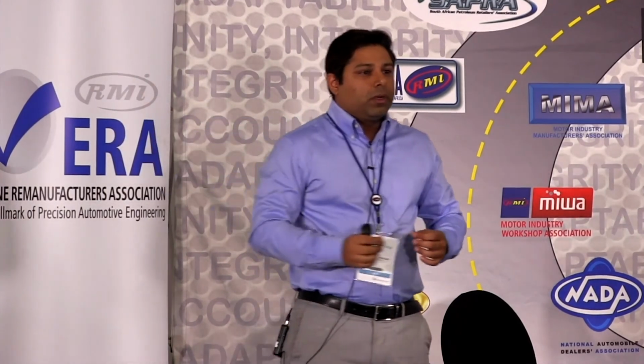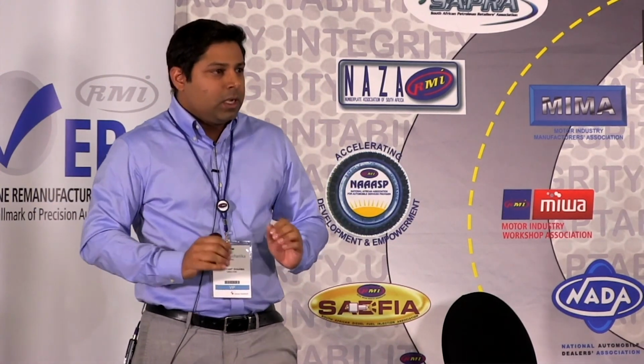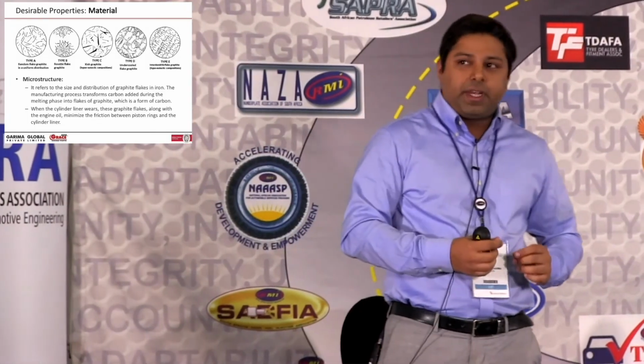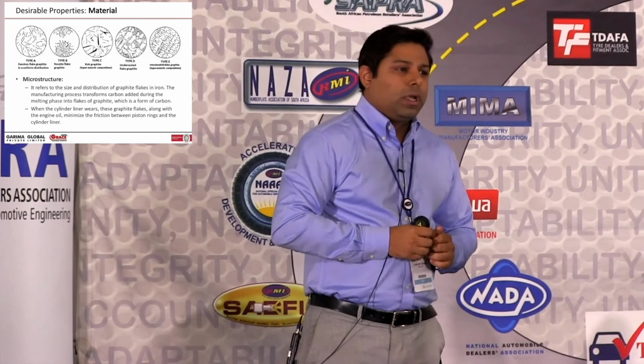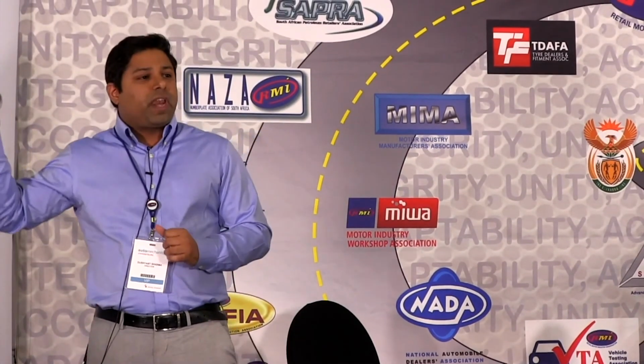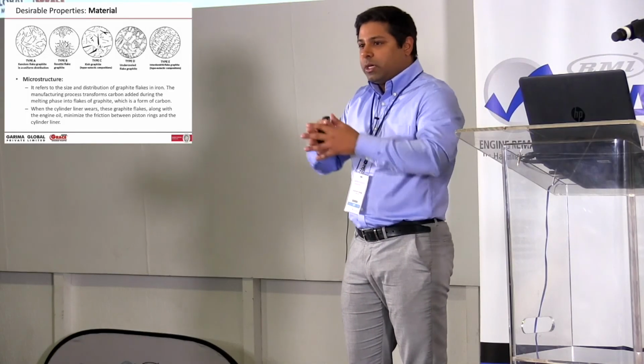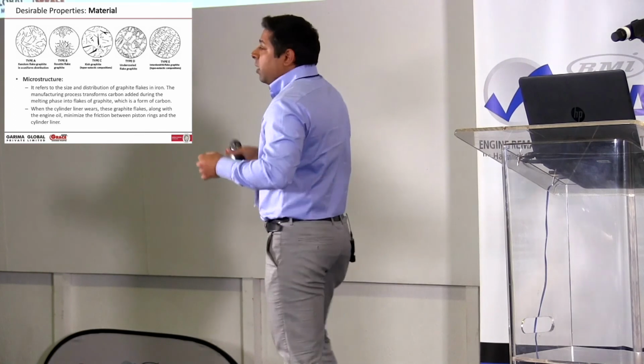During the melting phase, we put some carbon, which is by far the largest addition percentage-wise, into the cast iron. Then when we put this molten metal into a rapidly rotating mold, and this is called centrifugal casting, the cooling rate of this mold, and in turn the cooling rate of the molten metal inside it, transforms this carbon into flakes of graphite, which are the black flakes you can see in the diagram up there. And these flakes of graphite are extremely important. Their distribution, their size, the way they are distributed in the matrix of cast iron is extremely important to determine how the cylinder liner will wear over its life.